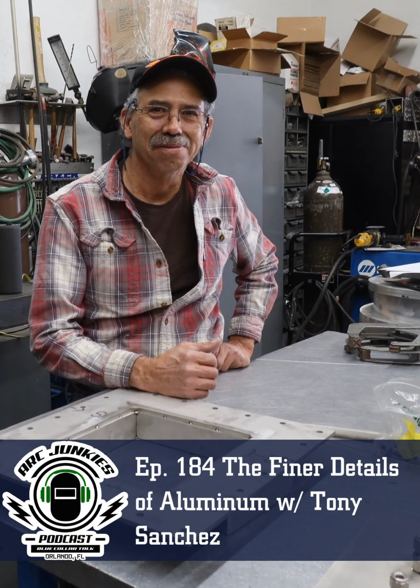And after all the 100%, after all the machining and everything, it had to pass dye penetrant. There were times you couldn't even tack things together, because you couldn't get the puddle to melt. So what I'd end up doing is heating up steel blocks really hot, get another helper, warm it up with the rosebud to about 350 degrees, and drop these blocks at about 600 degrees in certain areas. Then I'd start welding, because now my heat isn't running out, it's trying to come back to me. As soon as we get X amount, pull those blocks off and put fans and cold blocks back on it. The machine shop always said, man, you guys always warm everything up just so you can cool it back down. Well,